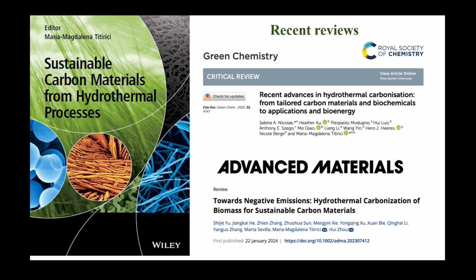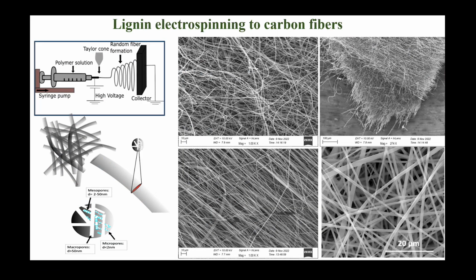And as I said, we are using the carbohydrate-rich fraction of biomass: cellulose, hemicellulose, carbohydrates. But we all know that in lignocellulosic biomass, there's cellulose and there's lignin. So we have another process of producing carbon in our group, which is by taking the lignin fraction of the biomass and putting it through an electrospinner, where you apply very high voltages, and you form this Taylor cone, and then you have a random fiber formation that you collect on a current collector. So you spin lignin fibers, which we then carbonize to form carbon fibers.